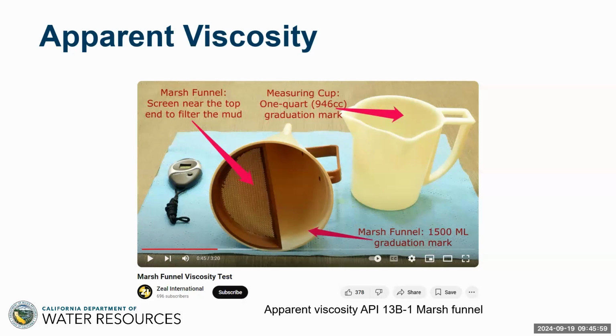Water is about 28 seconds. Typical, what we call high mobility grout, would be anywhere from 30 to 60 seconds. Beyond that, beyond 60 seconds, this test is less reliable and less accurate. And in fact, it doesn't relate to very dense high mobility grouts. Typically, if you find that you're testing and it's more than, say, 100 or 120 seconds, that means that basically the grout's too thick to pass through the system. Next one.